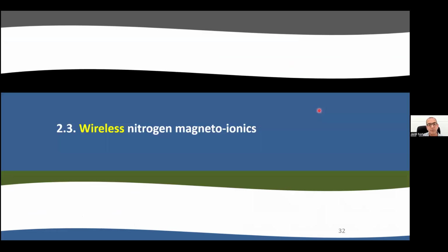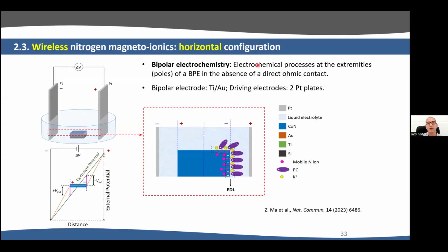So now, next, what I want to show you is something funny, because we can induce this magnetoionic effect without contacting the sample with any wire. So we can induce this for wireless applications. We use a phenomenon from electrochemistry called bipolar electrochemistry. In this case, we place our material inside a liquid electrolyte. We have two platinum foils immersed in the liquid. We apply voltage between the two platinum foils, but the sample has no electric contact.